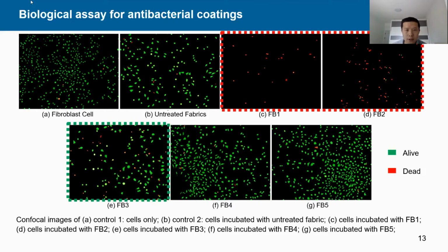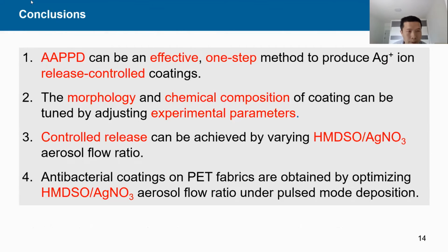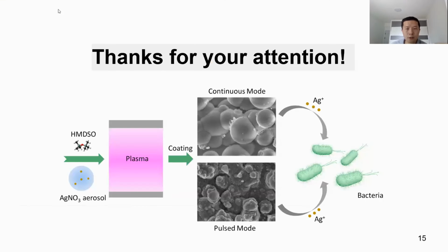So to conclude, this AAPPD technique can be an effective one-step method to produce silver ion release controlled coatings. The morphology and the chemical composition of coatings can be tuned by adjusting experimental parameters, and controlled release can be achieved by varying HMDSO and silver nitrate aerosol flow ratio. And antibacterial coatings on PET fabrics are obtained by optimizing HMDSO and silver nitrate aerosol flow ratio in the pulsed deposition. And thanks for your attention. And I'm looking forward to your comments.